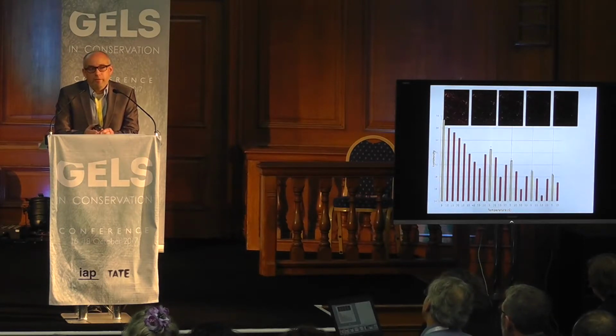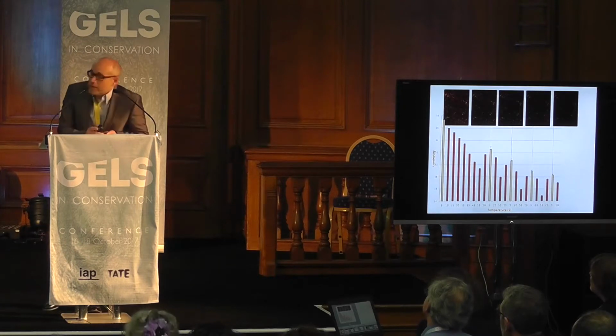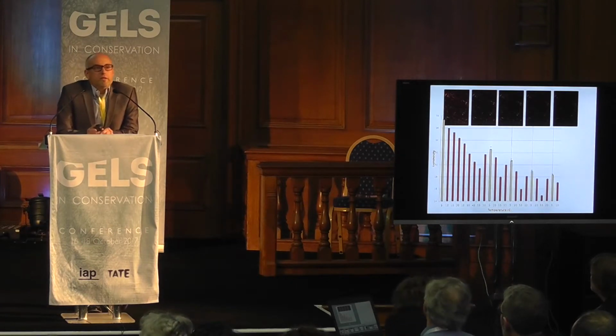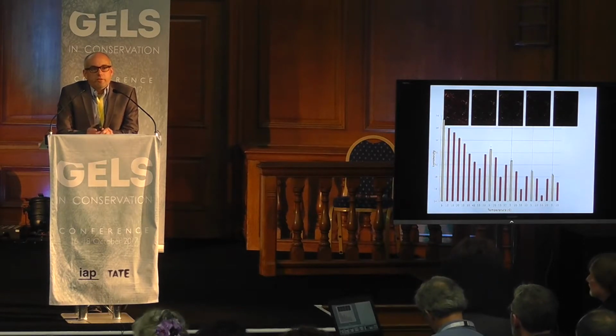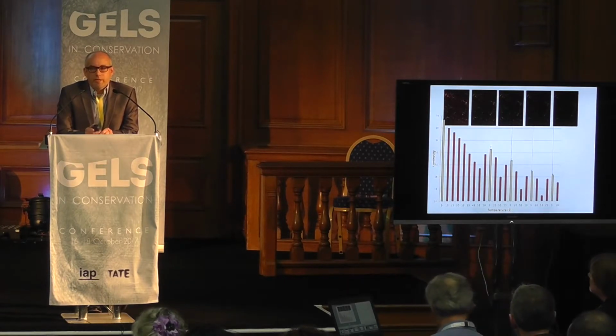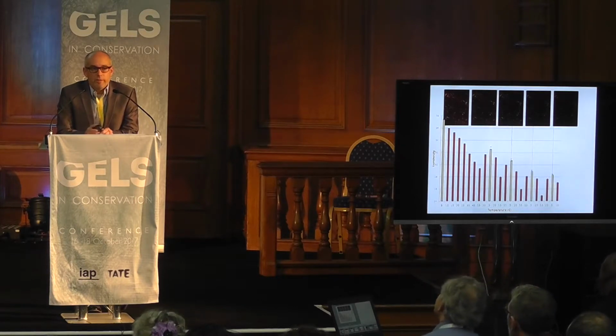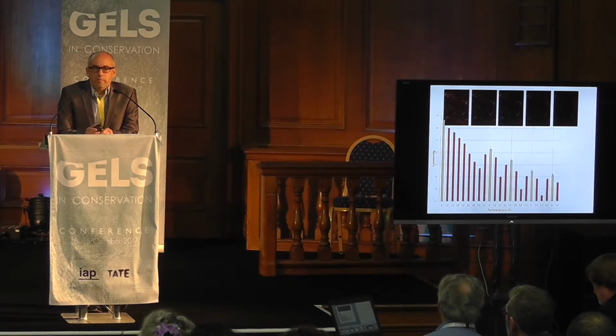We've fingerprint powdered the surface of this paint film, and then we can monitor it. And as you see, the luminescence, possibly, yeah, you can see. The one on the left is brightly colored. So as we increase the temperature, the luminescence on the surface of that paint film decreases, which means the surfactant we know is going into the paint film, but it also means that the soils are moving with that surfactant into the paint film. And this was an aha moment for Richard and I, because we had long known the movement of surfactant, but we really wanted to associate how surfactant moves with soils.